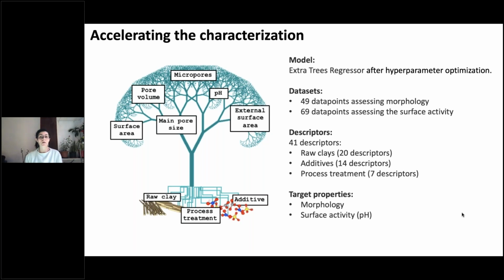2 data sets were employed. One assessing the morphology containing 49 data points, and the second one assessing the surface activity containing 69 data points. The descriptor space were identified by 41 descriptors grouped into 3 main classes: raw clays, additive and process treatment, and the target property were the morphology and the surface activity in terms of pH.